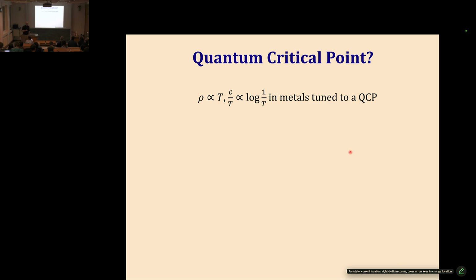A very recurring theme in the study of strange metals, and conceptually a very natural way to get a breakdown of Fermi liquid theory, starting from a Fermi liquid, is to tune the system to some kind of quantum critical point. We saw a very trivial form of a quantum critical point, namely a Lifshitz transition or Van Hove singularity. There are much more interesting kinds of quantum critical points. For instance, we can tune a Fermi liquid to a point where the system is just on the verge of breaking some symmetry spontaneously, developing some kind of magnetic order or charge order. And when you do that, you'll get a pileup of low energy excitations, which are the collective fluctuations of the incipient order parameter of the system.